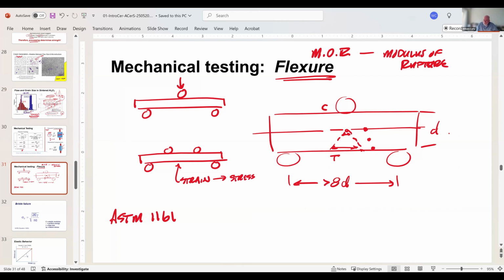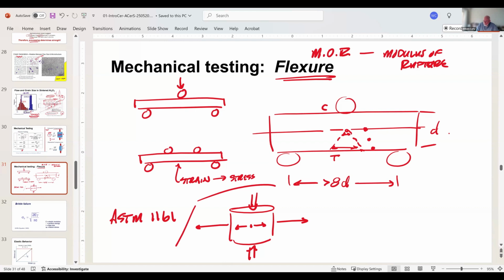Okay, so we're going to talk about that a little bit. I'm going to make one other comment. By the way, in my cylinder for compression testing, the reason the strengths are so high is because when I press like this on the system, I end up with a Poisson's ratio effect. This side wants to go out, that side wants to go out, and in the center I create a tensile force, and my failure initiates in the center. So it takes a lot of load to get this to fail. That's why we like this test for concrete specimens.